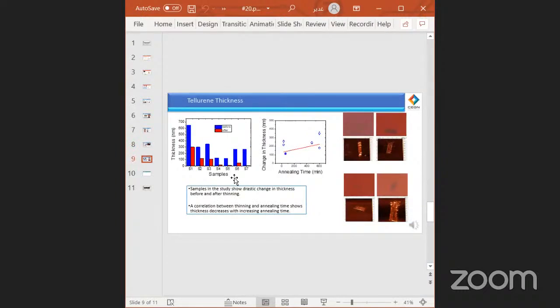In this slide, we can compare Te thicknesses before and after thinning, where the first sample has a thickness of about 600 nanometers. And after thinning, it shifted to almost 300 nanometers. And the fourth sample, we started with nearly 150 nanometers, and after thinning, it was less than 20 nanometers. And finally, the seventh sample started at 270 nanometers and thinned to almost 6 nanometers in thickness. Each flake can be thinned more than that by repeating the annealing cycle.